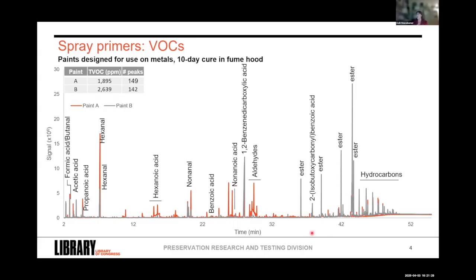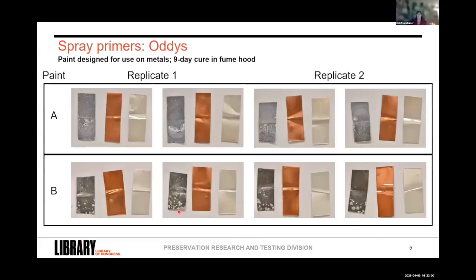We tend to kind of divide this 60-minute run up into before 20 minutes. So those are the more volatile compounds likely to come off in the earlier lifetime of the material. And then your last half of the chromatogram is the larger compounds that are going to be more slow and persistent to be coming off of the material. And we were seeing those as the carboxylic acids across the entire chromatogram, in addition to aldehydes and esters, not as favorable compounds either. Which meant when we got our Oddy test results out, surprise, surprise, not really.